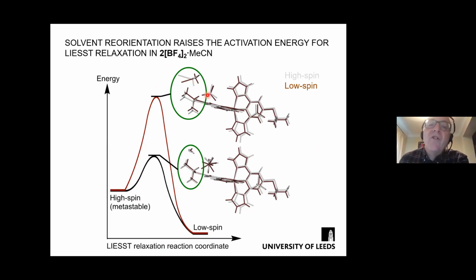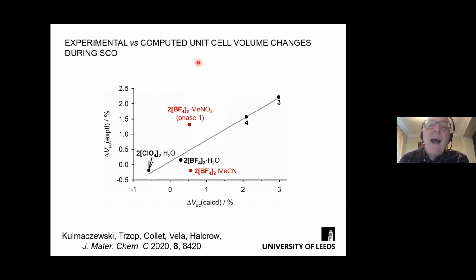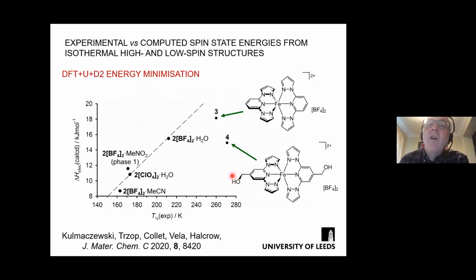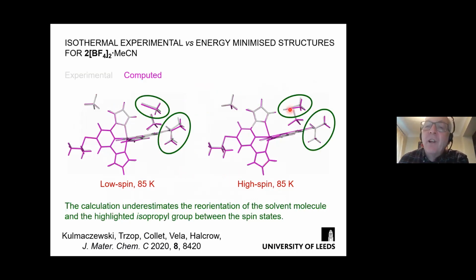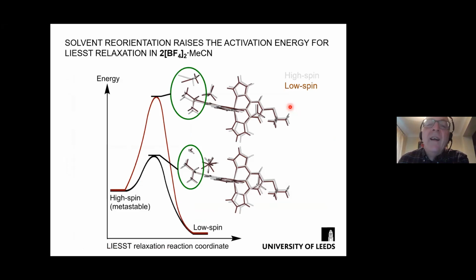And in fact, this structure change is so large that we can say perhaps that this is the thermodynamic structure of the lattice, but the real crystal cannot access this thermodynamic structure because the change in the solvent molecule is too large and the activation energy is too high. And so it's not possible for the crystal to access this thermodynamic minimum. The crystal almost becomes trapped in a false minimum during its LIESST process. That's how I understand it. Sometimes I get arguments from computational chemists who don't like this explanation, but I'm an inorganic chemist and this is how I understand it for now.